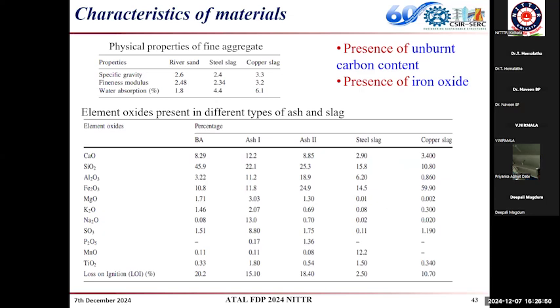So these studies we have carried out, and for developing this special concrete, as I mentioned, these are the two criteria we have fixed: presence of unburnt carbon content and presence of iron oxide. These two help in improving the conductivity. So we have taken many industrial byproducts and we have tested the unburnt carbon content. This can be tested by using loss on ignition, and the presence of iron oxide, Fe2O3 content, by chemical composition.